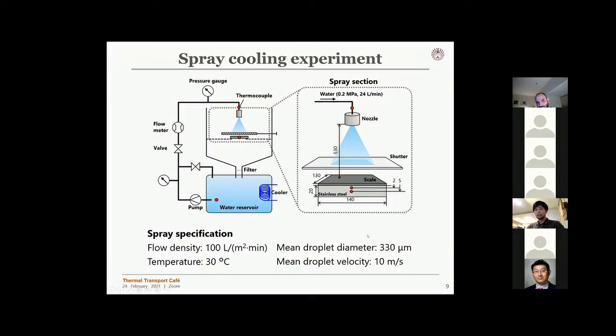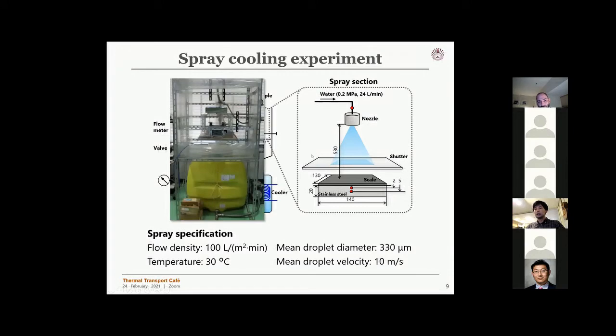This is some specifications of the spray used here. The flow density is around this, and the mean droplet diameter was around 330 microns. Droplet velocity was 10 meters a second, and we kept the temperature of the water at 30 degrees Celsius. This is a picture of our setup.